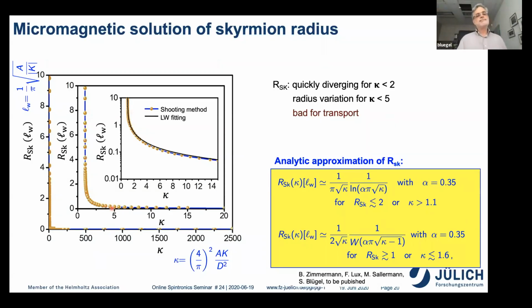But imagine, for example, you want, so this curve is with respect to the domain wall width. So imagine you want to have a 10 nanometer Skyrmion. So now you have two parameters, two things you can work on. You can have a small kappa and a large domain wall width, or you can have a small kappa and a small domain wall width. Both might give you the same radius. And you have three quantities to vary, which are the exchange, the anisotropy, and the Dzyaloshinskii-Moriya interaction.